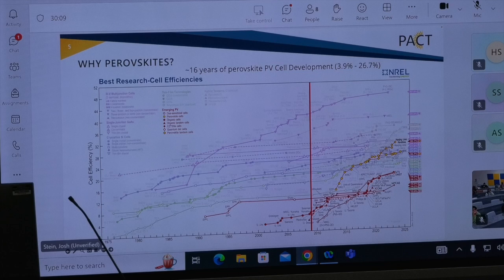So now if we switch to perovskites, you need to focus on the red circles with the yellow in here, and you can see that it started, the record cells, this horizontal line here was when the technology was invented in the laboratory. And the red circles with yellow dots are the perovskite solar cell record efficiencies. And you can see that for single junction devices, those are the circles, by 2024, we reached 26.7%.